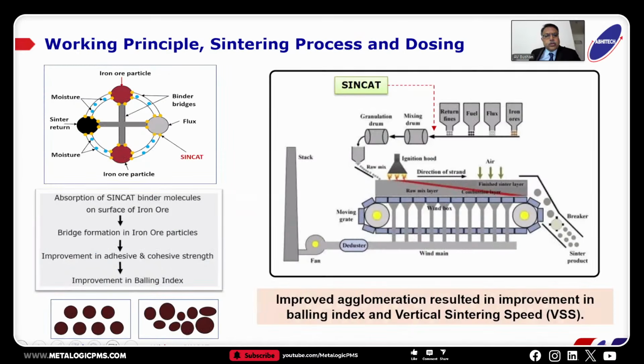So I will quickly go through the working principle of the sintering process. SynCat is basically a product which has been designed to adsorb the binder molecules on the surface of iron ore, and it forms a very good bridge between the iron ore particles. It increases the bonding strength, both the adhesive and the cohesive strength, and therefore improves the balling index. So when this happens, you have an improvement in the overall sinter quality and a reduction in the fines because the strength of the sinter also improves. Next, please.